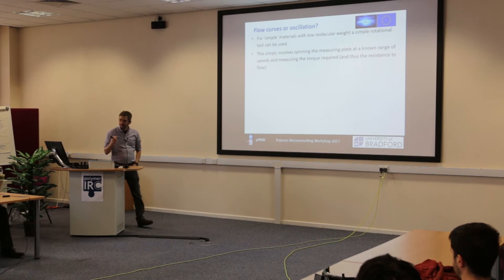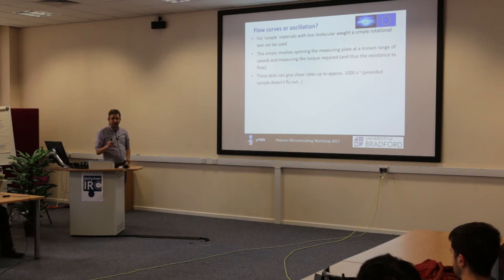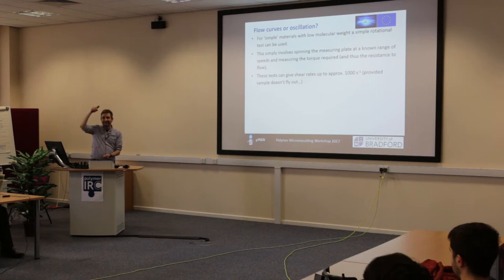However, if you try and do this with polymers, what you do is you shred them, you rip them apart, okay? Because you've got these long chain molecules, as I say, they start to align. If you keep going and keep straining and keep straining, it's the equivalent of doing a tensile test on a liquid, okay? You will rip the material apart.